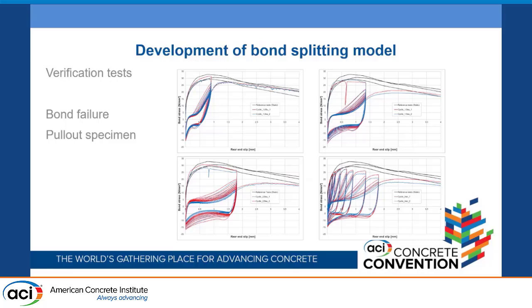So this is an example where we had bond failure. This was a confined test, bond failure, pull-out specimen. The first case was done with 10 cycles at SU, then 10 cycles at 1.5 SU, 10 cycles at 2 SU, and this was the increasing slip protocol, which we can see is slightly conservative compared to the protocol which is right now used for cast-in rebars, but still is quite decent, especially for the pull-out specimen.